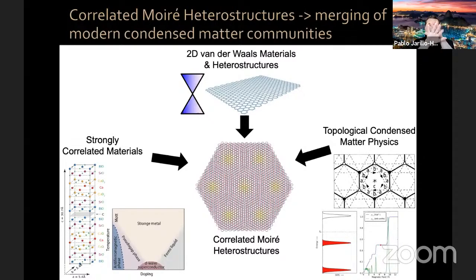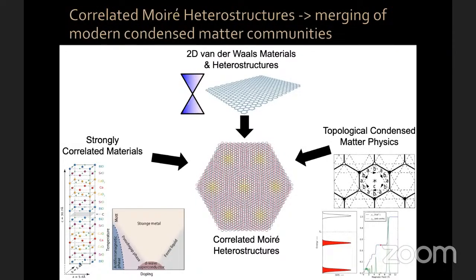That alignment with that lattice breaks a symmetry known as C2 symmetry, because now underneath the carbon atoms, you have one carbon atom on top of a boron atom and another carbon atom on top of a nitrogen atom. So that leads to a broken symmetry in the system. And that broken symmetry is responsible for the quantum anomalous Hall effect and for the presence of ferromagnetism. And it's again interaction induced due to the breaking of that symmetry. Very good. But I thought it was pure graphene, and then I didn't understand.